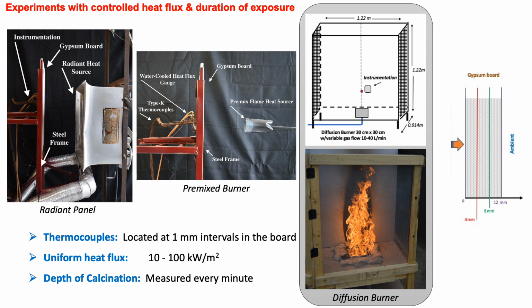We then did a pre-mixed burner. In the middle photo here is a pre-mixed flame that we exposed a similar sized drywall to. And then our last series of experiments with heating is this diffusion burner, where we used a gas burner and exposed the drywall to the diffusion flame. The depth of calcination was measured every minute of exposure, and we plotted that data in our experimental results.